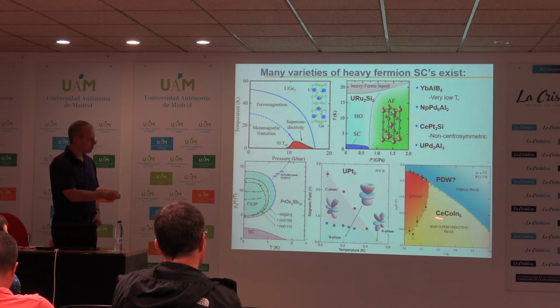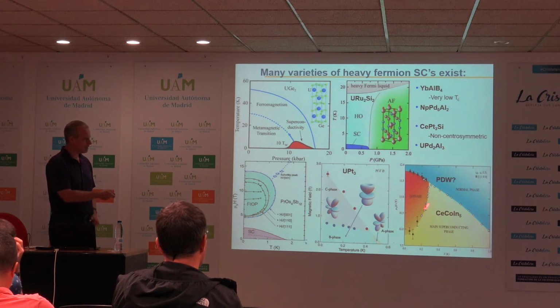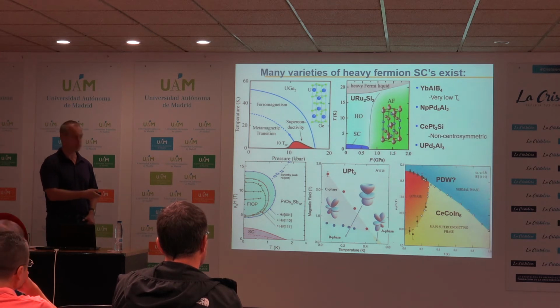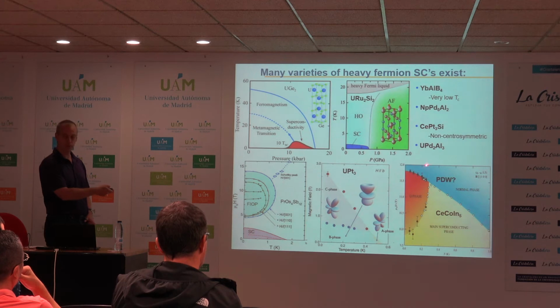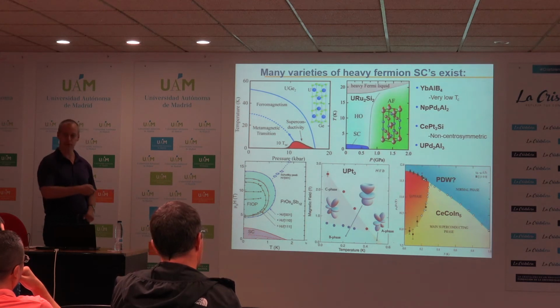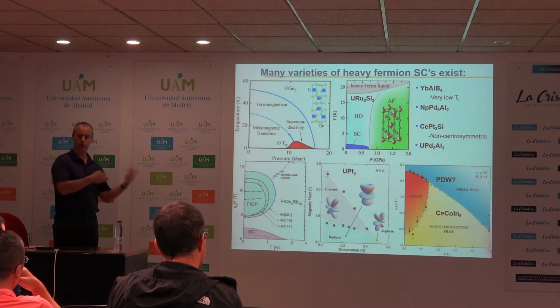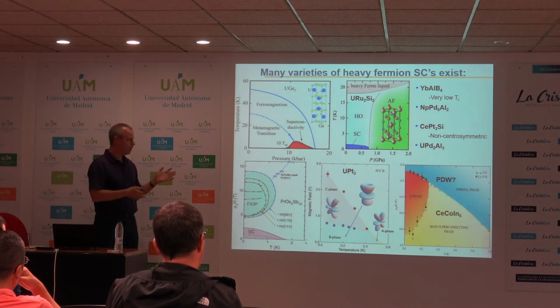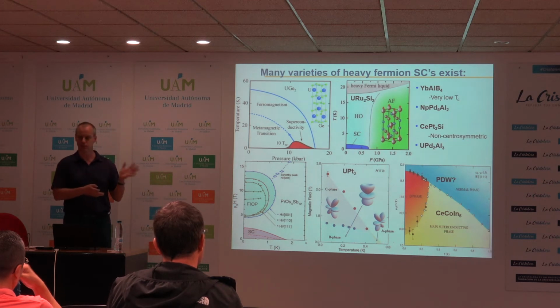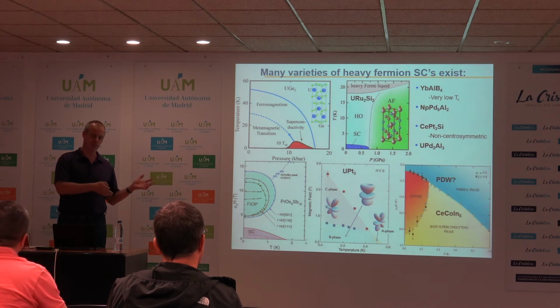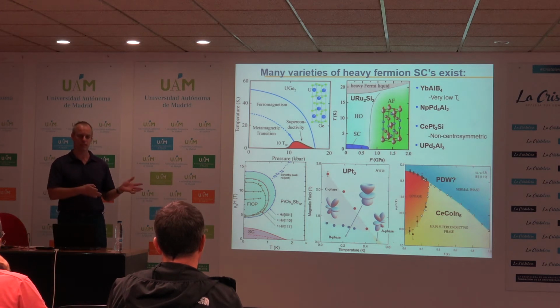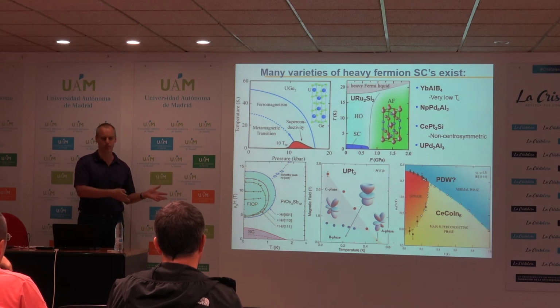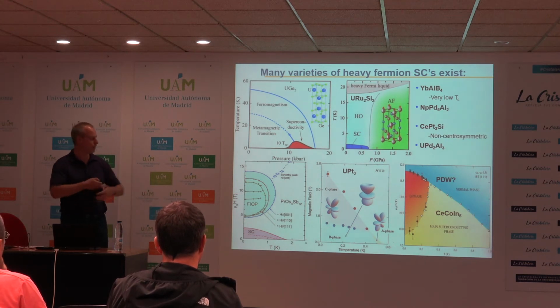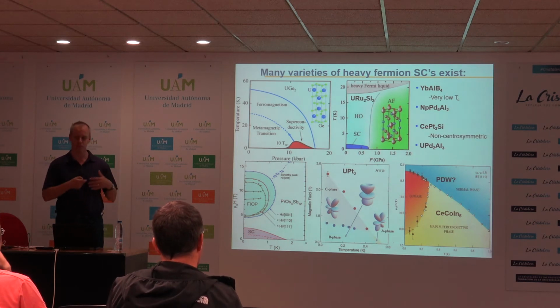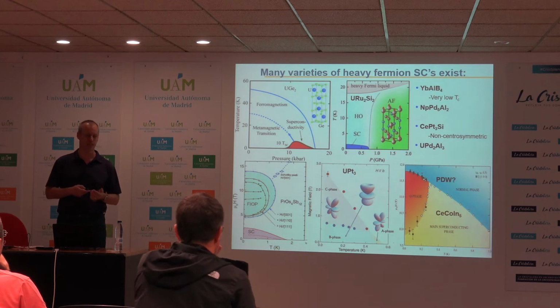Here's an example of cerium-cobalt-indium-5. In the high field, low temperature part of the phase diagram, there's magnetism that seems to live only within the superconducting state. So as you go above Hc2, actually, you don't find magnetism anymore. There's been evidence for pair density waves. So we heard arguments for pair density waves in cuprates. And I hope one message that you take away from this talk is that, in fact, a lot of the phenomenology of heavy fermions mimics itself in the other systems, in 3D systems. So whether it be pnictides or cuprates, there are differences, but in fact, you see the same kinds of phenomena appearing in these systems.